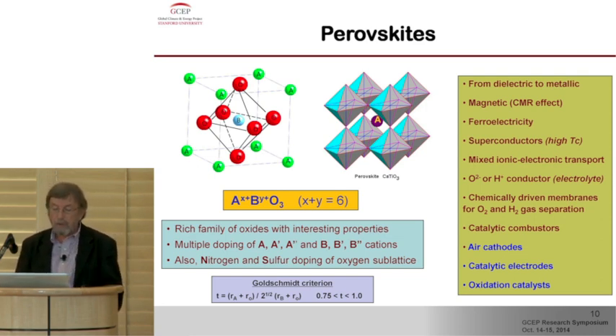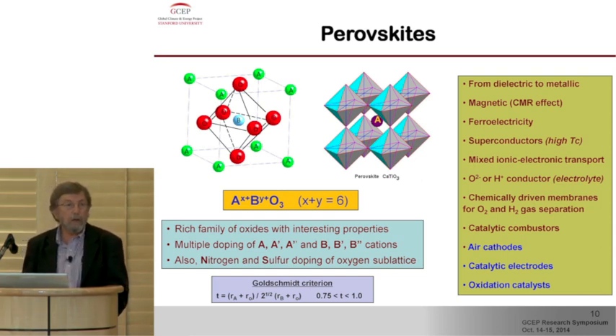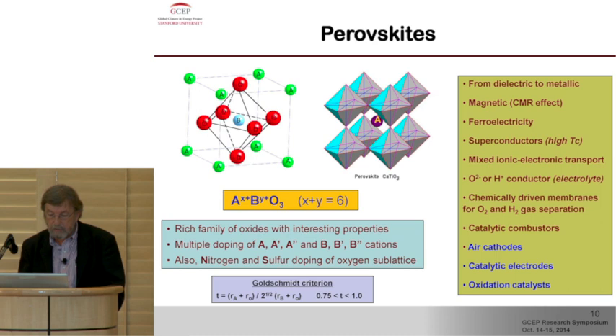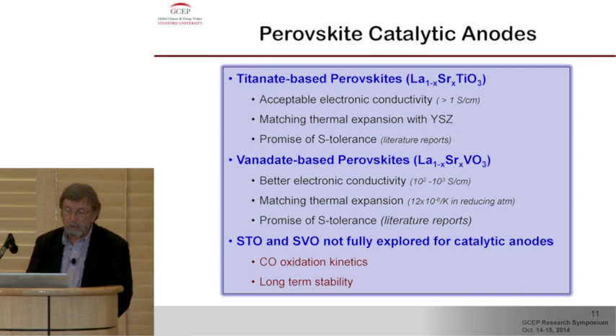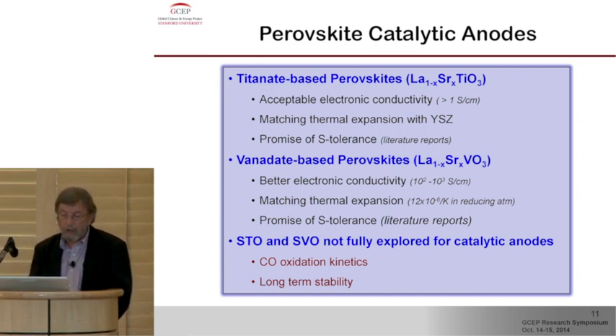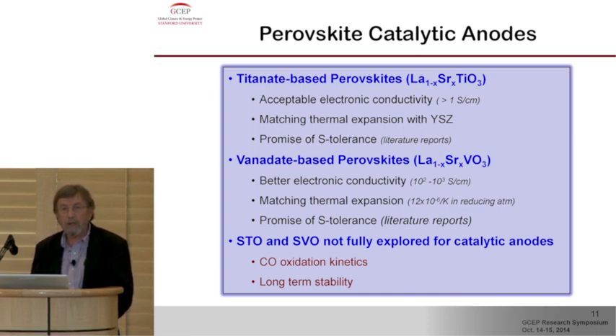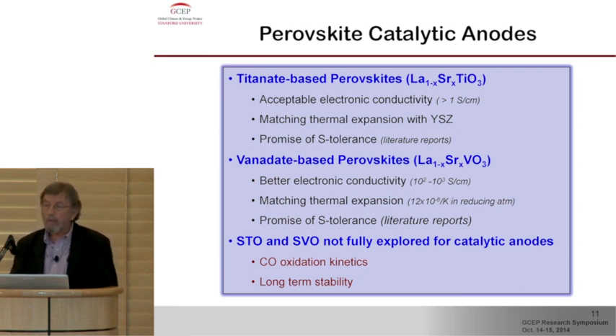And because of the versatility of this whole list of very interesting electronic, ionic, dielectric, and catalytic properties that this family of perovskites exhibit, and I won't go into them, many of them are actually of industrial interest and being used in technology. So the two families of perovskites that we have identified so far are the titanate-based and the vanadate-based perovskites. They have not been really explored too much in the catalytic area, and there is some indication in the literature that these perovskites would have some stability against sulfur contamination.